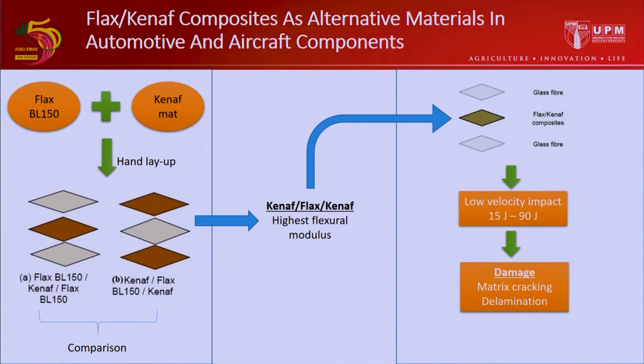For the Kenaf Flax glass hybrid composite analysis, it was found that as the impact energy increased, the energy absorbed by the specimen also increased. It demonstrated that more damage occurred at higher impact energy.